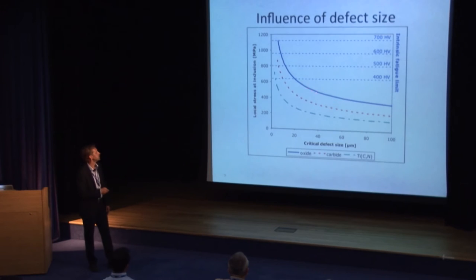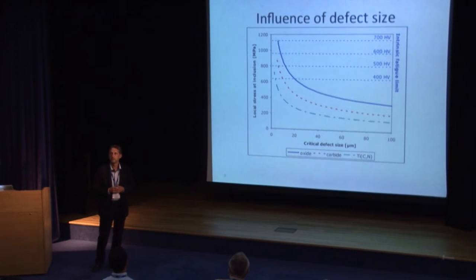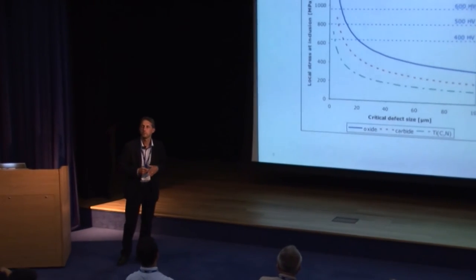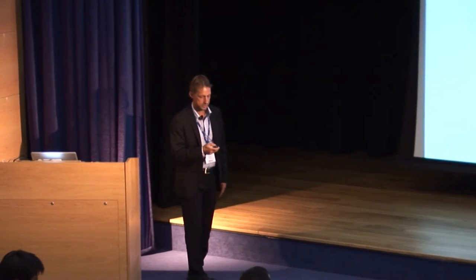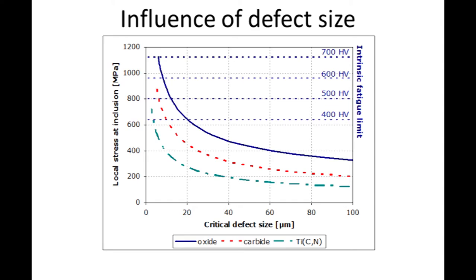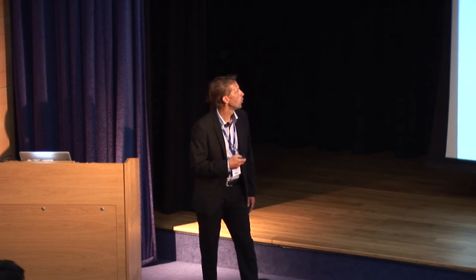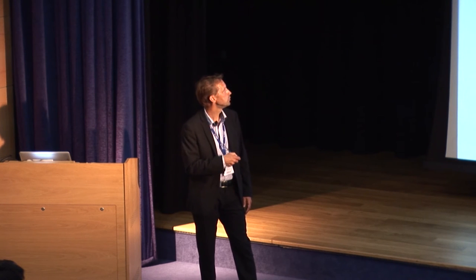All these curves are established from actual experimental tests made on rotating bending fatigue. And then you see how you can increase the fatigue strength if you reduce the critical defect size. But of course, only up to a certain point, where you have the intrinsic fatigue limit that puts the cap on. For the high strength materials that we are interested in, the potential is dramatic. So there are still a lot of things to do to go up there.